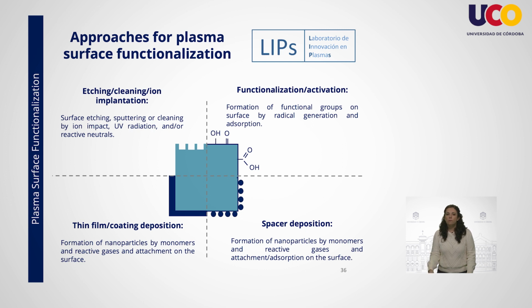In the case of nanoparticle formation, precursor materials are introduced into the plasma, where they undergo chemical reactions and physical transformations. The energetic conditions within the plasma facilitate the dissociation and recombination of atoms, leading to the creation of nanoscale particles. The versatility of plasma processing allows for precise control over the nanoparticle size, morphology, and composition by adjusting simple parameters such as gas composition, pressure, and power. Another functionalization could be considered film deposition.